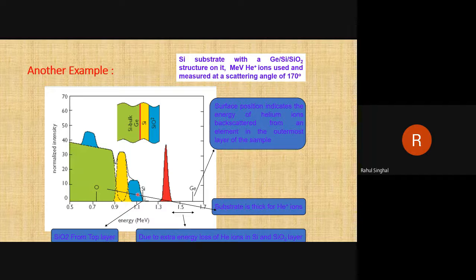Okay, so here you can also see the color coding. These peaks, due to the color, are for silicon. This color is for the silicon which is present in the middle layer. You can see that with depth, the silicon peak position is also varying. That is the depth profiling. How can you find out the amount of silicon present within the depth of your sample?